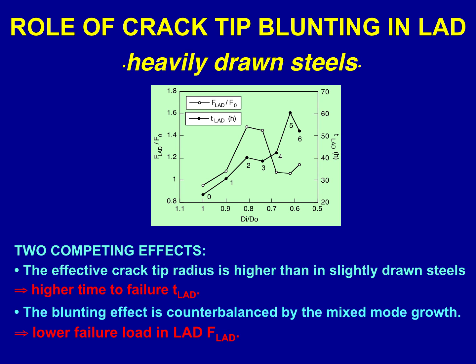Then, in heavily drawn steels, there are two competing effects. The effective crack tip radius is higher than in slightly drawn steels. It implies higher time to failure T-LAD, as this plot indicates. But, on the other hand, the blunting effect is counterbalanced by the mixed mode growth. Then it means lower failure load in localized anodic dissolution, F-LAD. This means that there are two inverse trends of increasing time to failure but decreasing failure load.